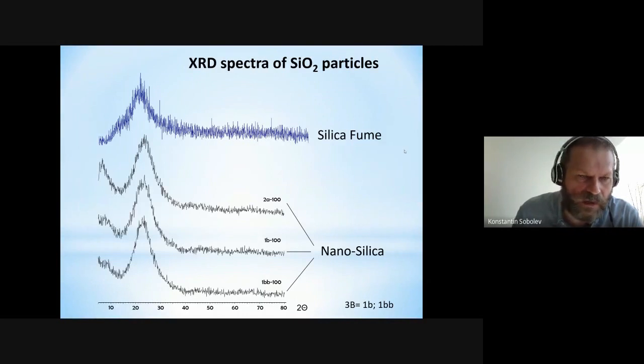So if we compare the structure of nanosilica to silica fume, you can see silica fume is a known amorphous product, and here we use silica fume with 95% or more, 98% of silicon dioxide. Nanosilica is 99.99%, almost like chemical grade amorphous silicon dioxide. So you don't have a crystalline structure, you have a perfect amorphous structure. They are very difficult to distinguish with simple X-ray diffraction. So X-ray diffraction cannot be used to characterize the products.